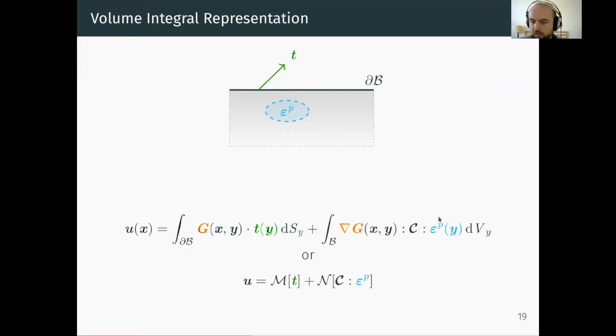What I did was to devise a method that is based on volume integral representations. So I have a half space with contact tractions and a distribution of plastic deformations. And what I want to do is to express my equilibrium displacements as a function of those two quantities. So for the contact tractions, I have this boundary term here, which is very similar to what I just showed before with boundary integral methods. And I have an additional term that takes care of the plastic deformation. And this expression here, I can only write if I choose wisely the Green's function here, G. This is just a shorthand for later on for the presentation. So I need to choose a Green's function that is appropriate so I can write this equation.